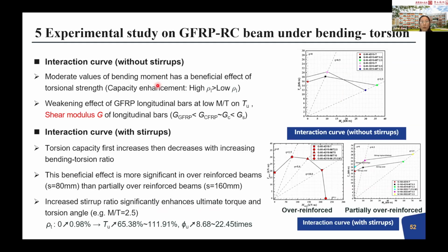First of all, for the beam without stirrup, we're finding that the longitudinal bars' effect will not be significant for the increment of the torsion. But this ratio has a significant effect in the steel RC beam. So this is the first phenomenon.